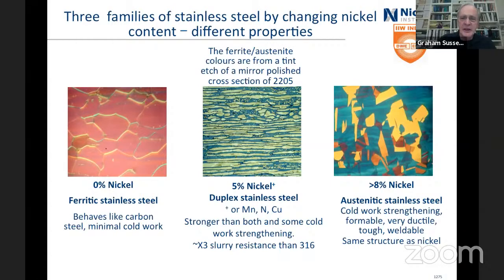The ferritic austenitic colours in this micro here, this is basically a cut section that's been polished and then etched because of the 2 phases. Here we have the green as the background ferritic, that is what it solidified as, and the white or slightly greenish colour is the austenite, which has grown out of that as it cools down. The black specks are what we don't want because that's saying that there's something wrong with the metallurgy, but we'll come back to talking about this and how the metallurgy develops and go from there.